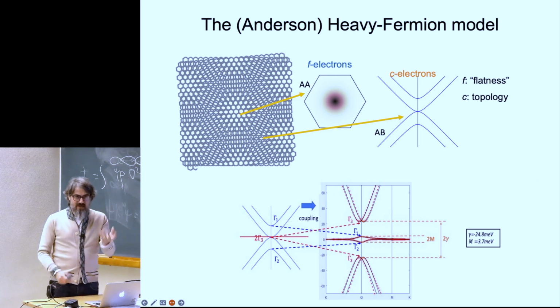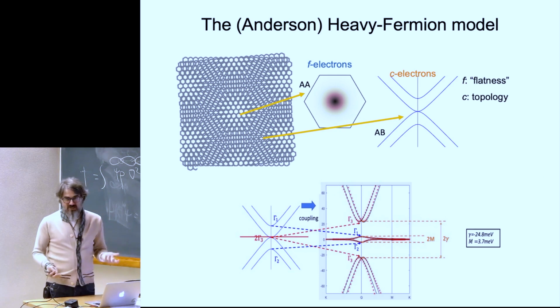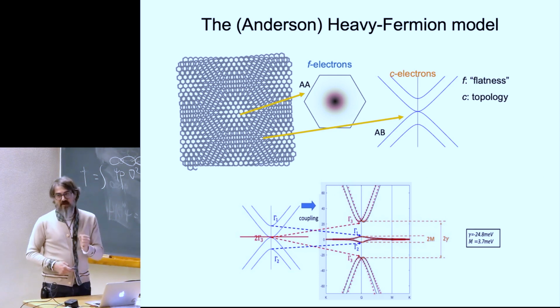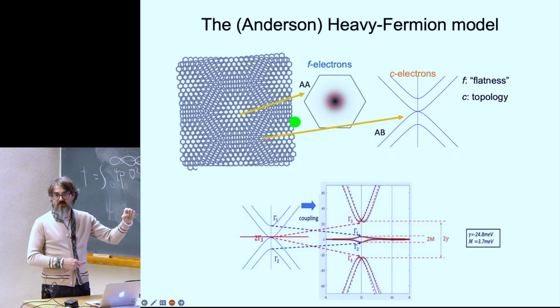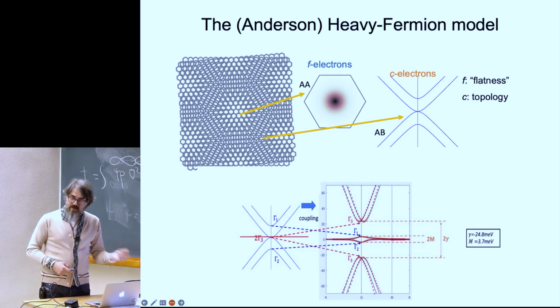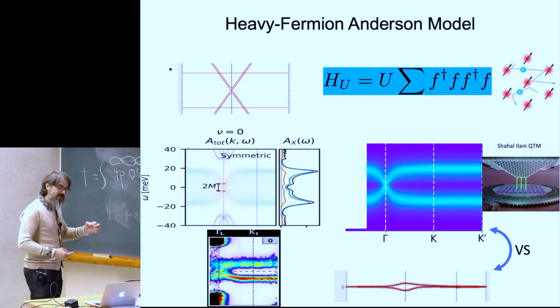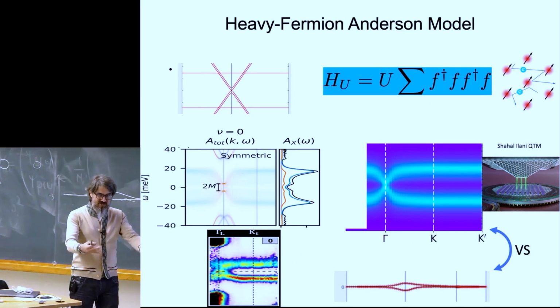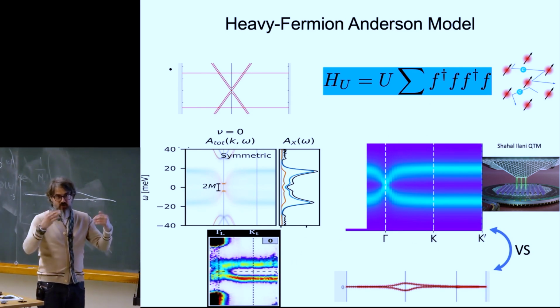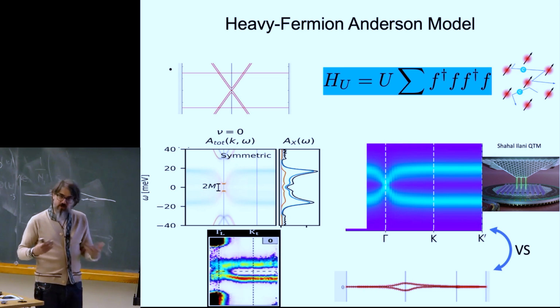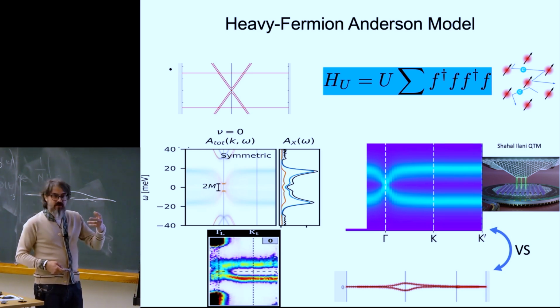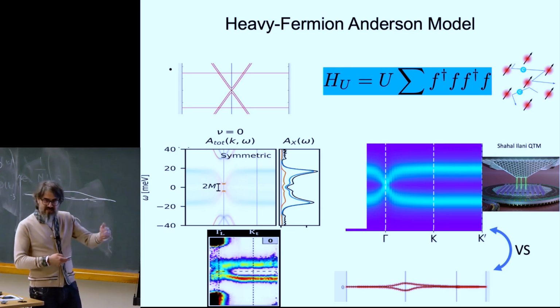So why is it important? As I said at the beginning, most of the interacting physics we can do is just changing bases because we can't solve it exactly. And this is a particularly good basis to change to. The reason for it is that most of the Coulomb interaction is now carried by the localized particles, which are the F electrons. So this is an Anderson model when you add interactions, and you don't add them by hand. Nothing here is added by hand. You just take the ab initio structure, you just compute these envelope functions analytically, then you project the ab initio structure onto these wave functions, and then you project the Coulomb interaction onto these wave functions, and you get some numbers. These numbers are obtained numerically. Now we can also obtain them analytically with some approximation, but the form of the Hamiltonian, the actual terms in the Hamiltonian, everything else is obtained analytically. So we're not guessing anything. We're not putting anything by hand.